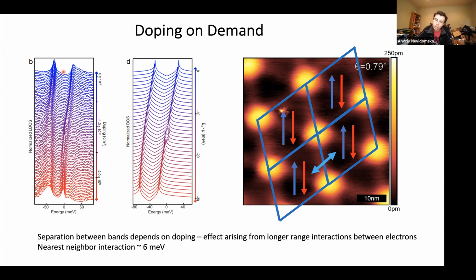I see. But would it not also be true, and I totally believe what you just said, that people often estimate the widths of the peak itself being maybe 5 or 6 or 10 meV, and then usually there is a gap up to the other bands, the rest of the stuff that happens around the gamma point. That changes depending on the twist angle, but people hope that it's maybe 15 or 20 meV, and therefore you have well-separated bands. But now you're saying there is another band that's 50 meV below what's called 0 here, and then what?